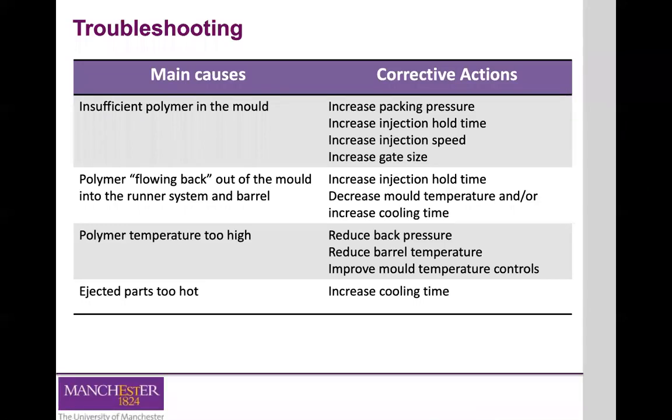We can also, without increasing the pressure, just extend the time that the pressure is applied. And by increasing that time, we ensure that the material has enough time to travel from the injection cylinder into the gaps that are formed. So sometimes it's just not a question of not having enough material. It can also be a question of not applying that pressure for enough time to ensure that the material reaches the areas that have these gaps and where the shrinkage is occurring.